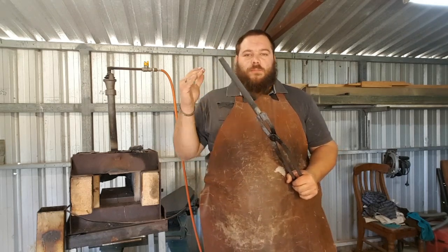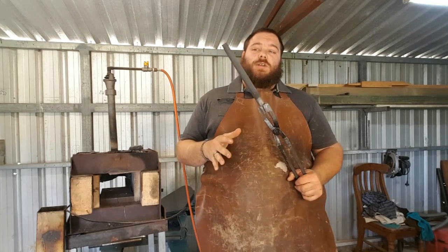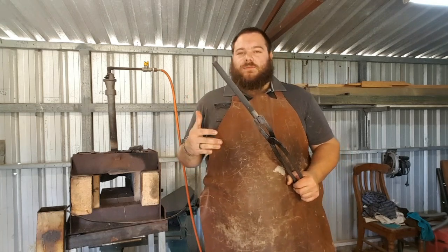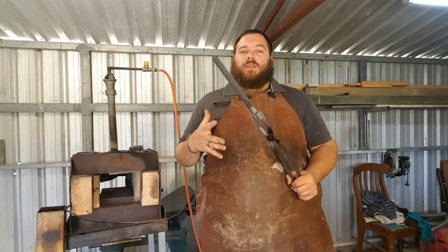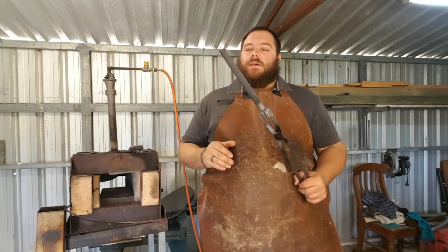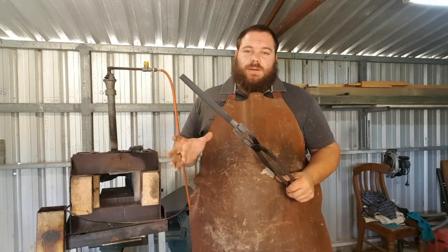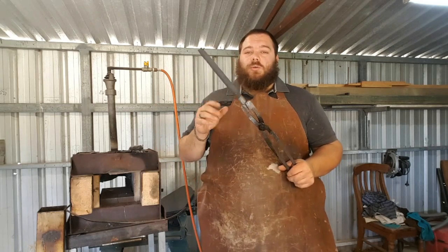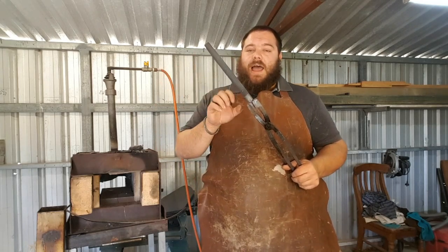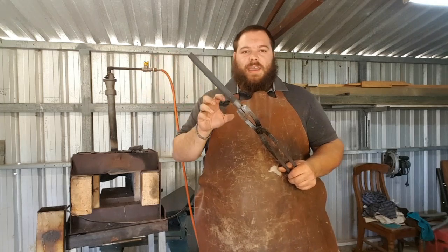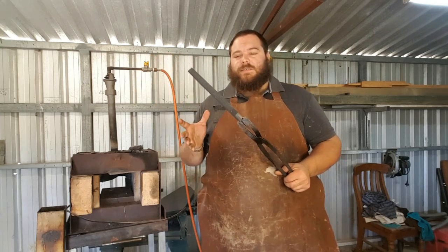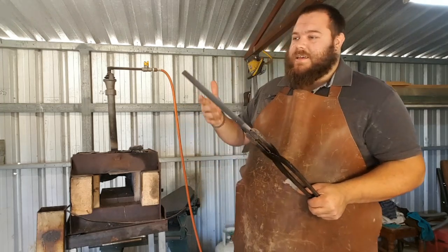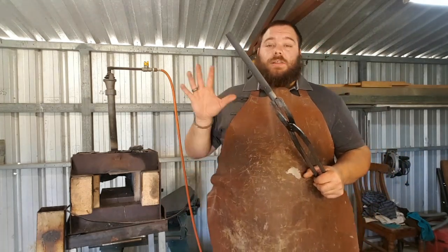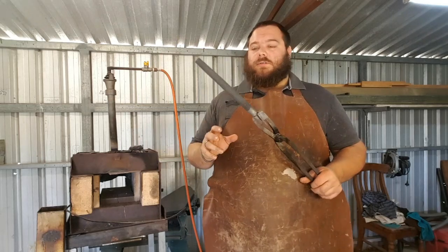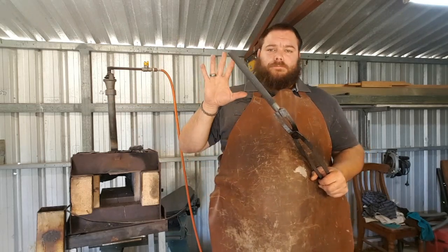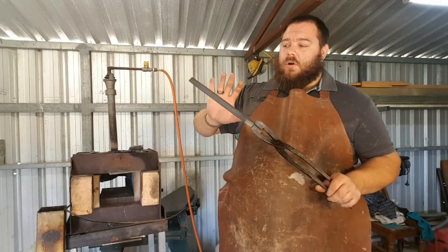It just requires it to go back through the recrystallization process, which I've tried to capture on film before. I will try and capture it in the future, but in a dark room, pitch black, if you heat to critical temperature and let it cool and watch it, you'll actually see the heat recede and then another, almost like a shadow of heat, pass over it again. It's called decalescence and recalescence. So that's a really good sign that you've got it all past the critical temperature. But basically, this is now completely normalized.